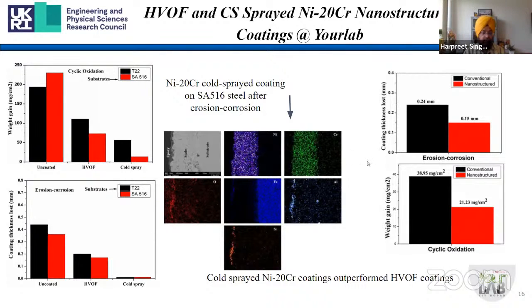So this is the comparison here, right? This is our conventional coating. This we called nanostructure, and we could see that erosion, corrosion, and oxidation were reduced. Moreover, we also established that this cold spray is slightly better than HVOF spray, at least for this combination, and so on.